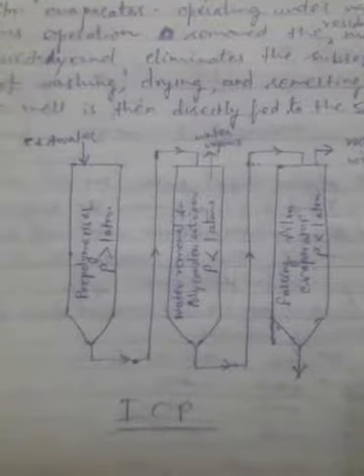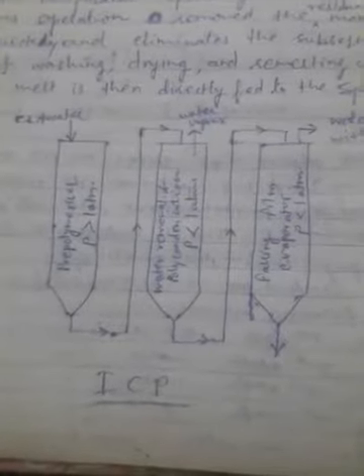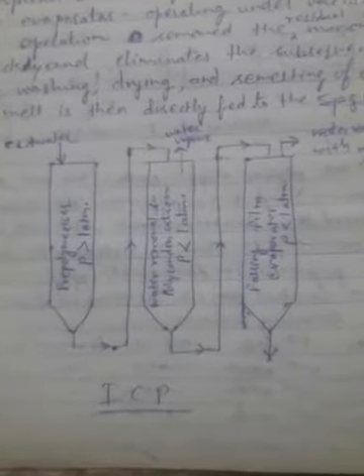This first step is named the integrated continuous process. Comparing with the conventional VK tube, in this modified process the polymer chips are not needed — the polymer mass is directly fed to the spinning cabinet. However, a very small quantity of caprolactam, say 1 to 2%, still remains present in the molten mass. This is the key difference between the VK tube and the modified integrated continuous process.